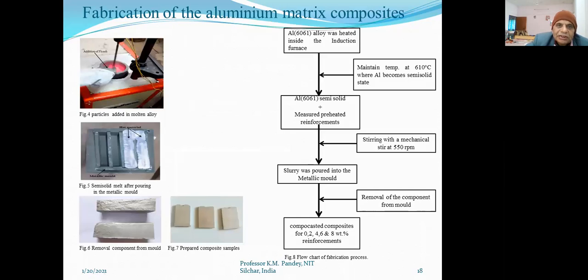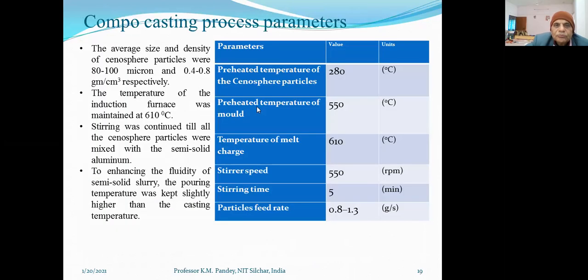And this is the fabrication of the aluminum matrix composite. So how they are fabricated is shown. Particles are added to the molten alloy, and here is the semi-solid melt after pouring in the metallic mold, and this is the removable component from the mold. Okay. And these are the prepared composite samples. So this is self-explanatory. Okay. Then the compo casting process parameters. These are the compo casting process.